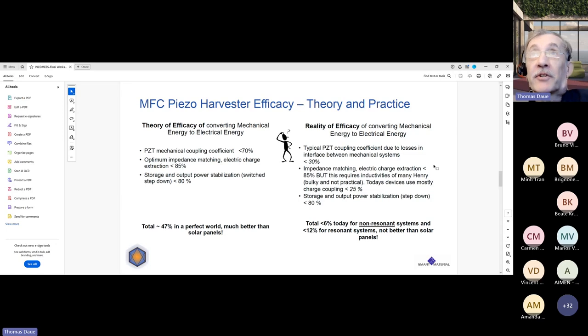But the reality is much different, as you already anticipated. In a typical mechanical setting, you seldom get more than 30%. It's normally less than 30% mechanical coupling, so it's half of it. The impedance matching is very difficult for the extraction. And exactly here is one of the biggest problems to use kinetic harvesters in any real application. You're really bouncing between a possible maximum, which you only reach using very large electric inductivities, like big Henry coils, which you don't want to do.